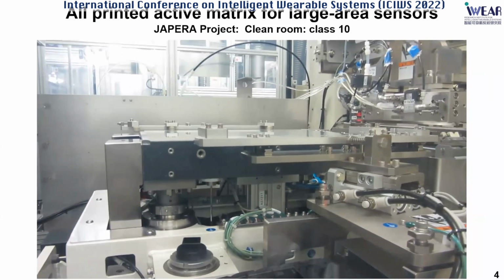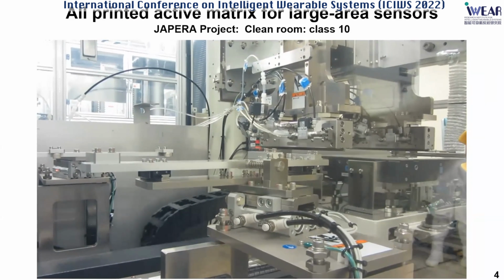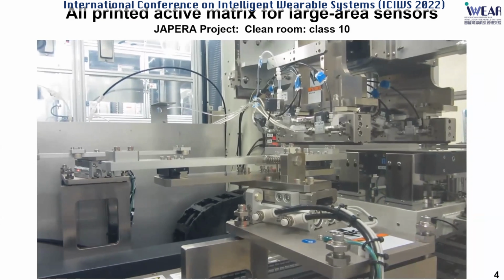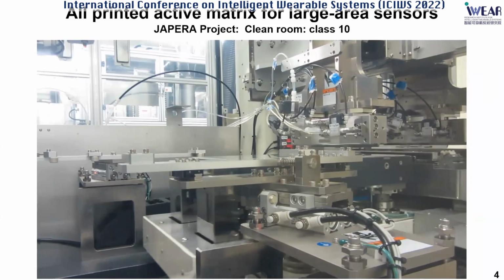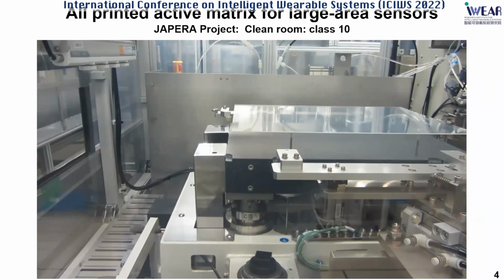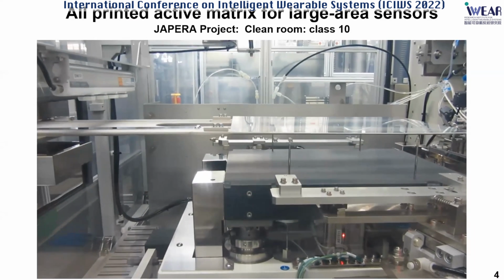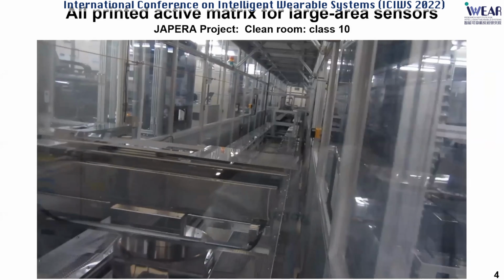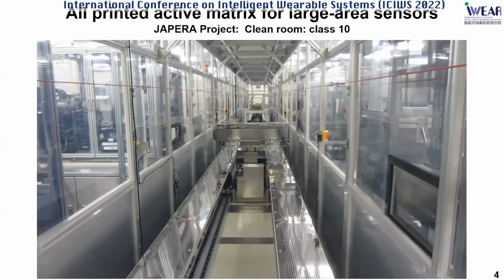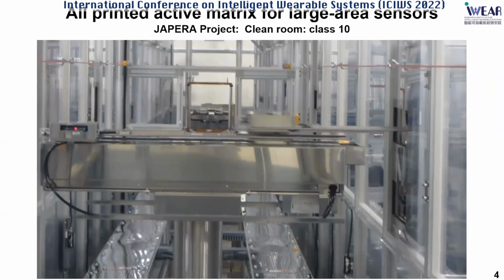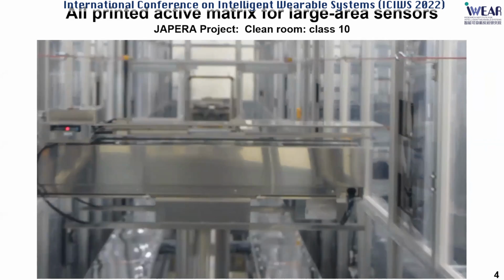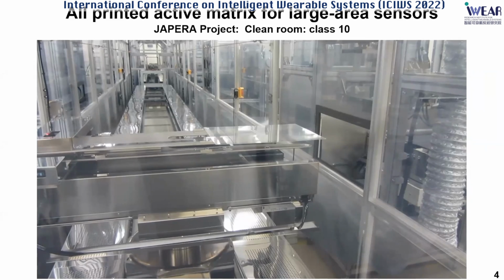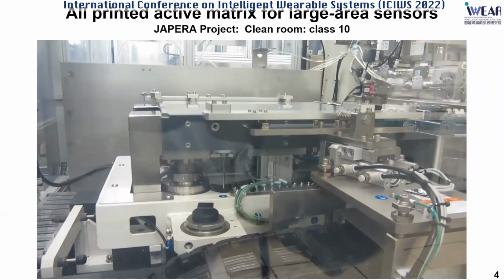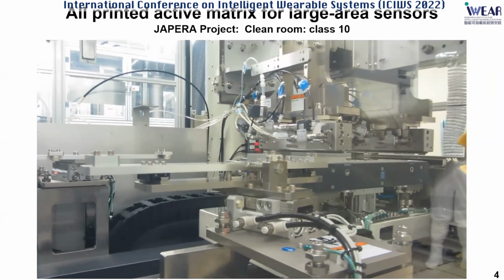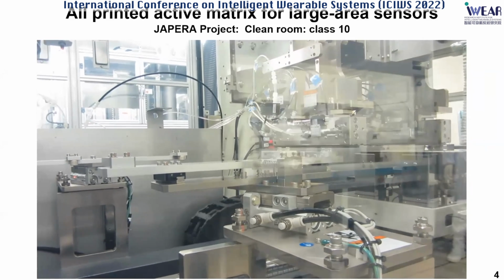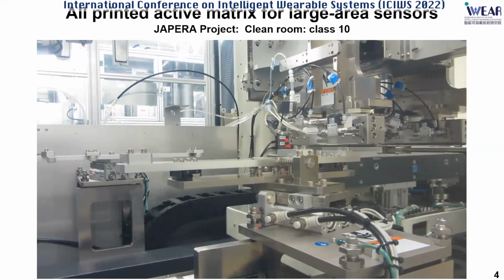So this movie shows you our production line to manufacture the active matrix for large area sensors by combining printing processes, which include inkjet, screen printing, and gravure offset. Here you can see the robot arms transferring the thin plastic foil that is temporarily supported by the glass substrate, and then fabricating the organic thin film transistors with high spatial resolution. Because all the manufacturing environment is kept very clean, like class 10, we can improve the yield and quality of thin film transistors very precisely.